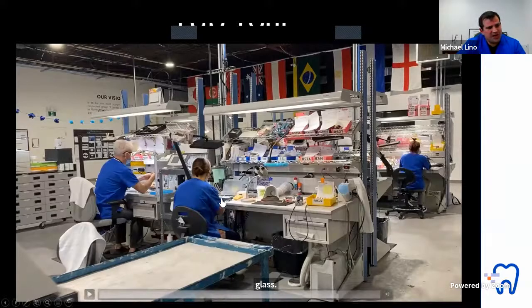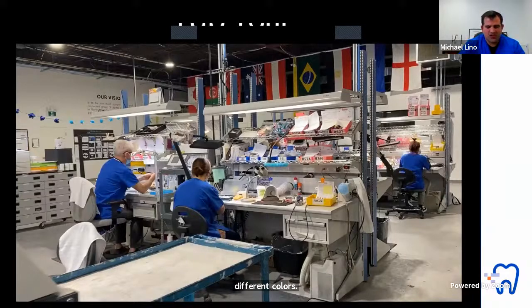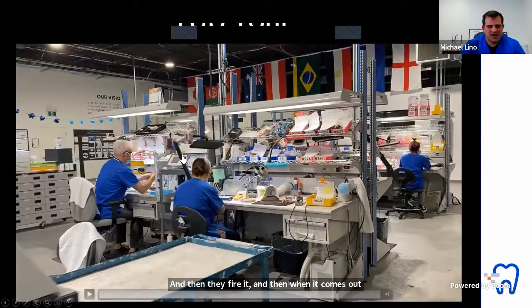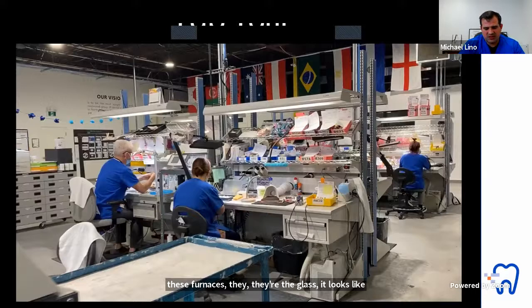On this tray here, there are different powders of sand and different colors. And they build up on top of that metal frame that I told you about, they build up like little sand castles, but in the shape of teeth. And then they fire it. When it comes out of these furnaces, the glass looks a little bit like the shape of a tooth. It shrinks. And then they have to do another buildup of sand on top of it. And they fire it again. Once that's done, it usually takes about 2 bakes. They trim and glaze it, and at the end of it, it looks like a tooth and the color looks like a tooth.